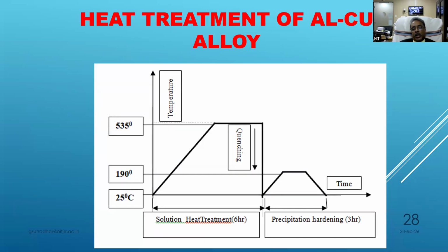If the basic alloy is, say, LM11 or LM25, normally it is heated to 520 to 535 degrees. Then this is the soaking zone. It depends on the thickness of the casting. It may be a minimum of 1 hour, or up to 8 hours to 12 hours. Then it is immediately quenched to around room temperature, stays for some time, and then is heated again to 170 to 190 degrees. This part is called aging. Basically, aging is also called precipitation hardening.